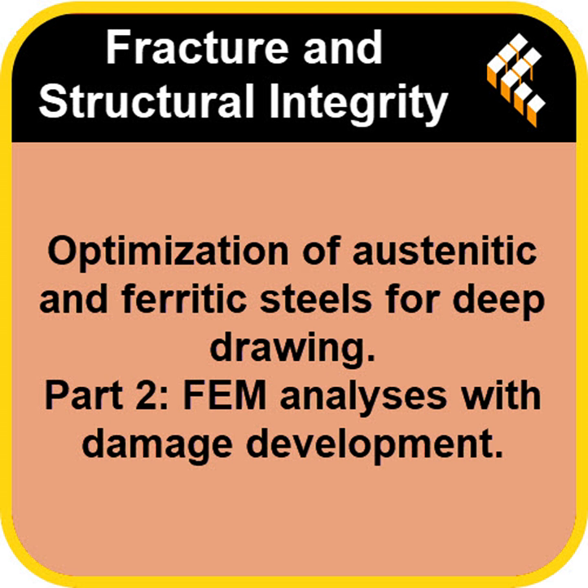And did it work? Was the final deep drawing simulation accurate? Incredibly accurate. The validated FEM model predicted the Erichsen index, that key depth measurement, with an average error of less than 3% compared to the actual physical Erichsen tests they ran. That's remarkable for such a complex process.